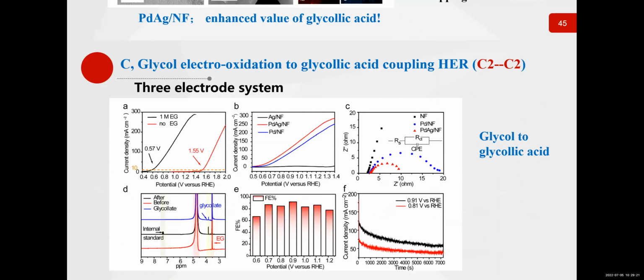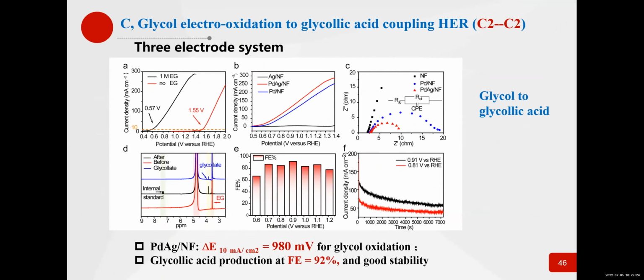Here it shows that by using this kind of catalysis, by adding glycol, you can see the potential reduction is very significant. The potential reduction can be as high as 980 millivolts. It's about 1 volt. It is indeed a very remarkable reduction of potentials. And the Faraday efficiency for the glycolic acid production is 92%. It is indeed high enough. And it also shows very high stability in the electrocatalytic process.